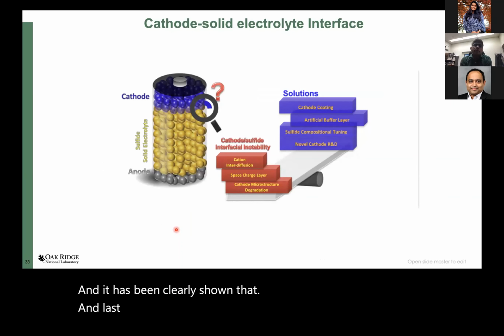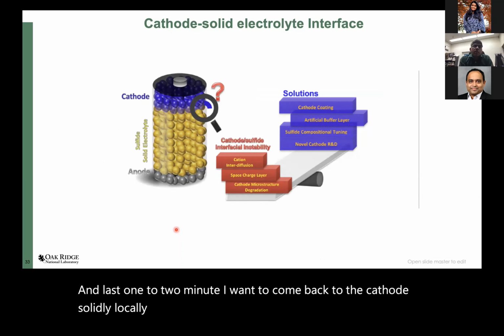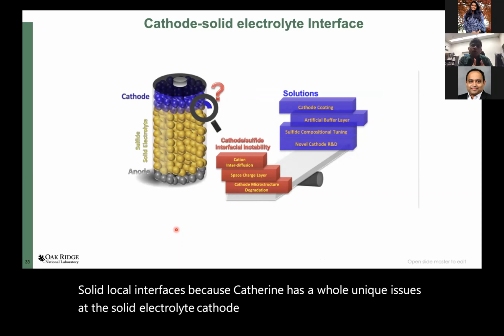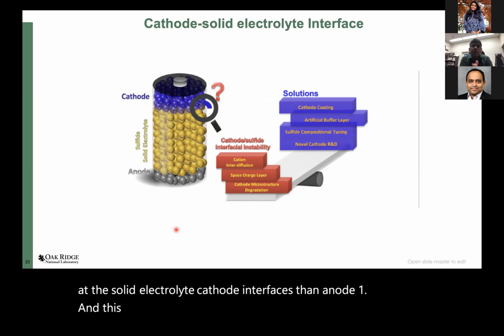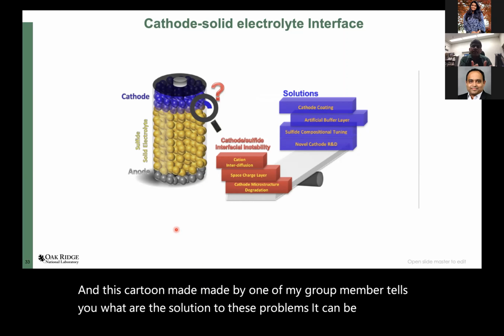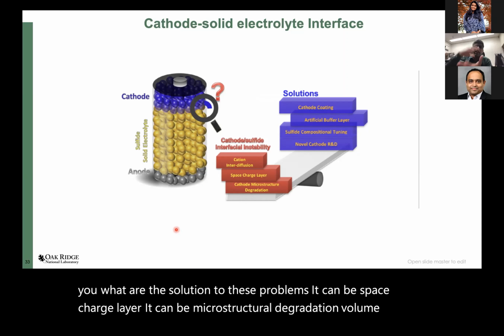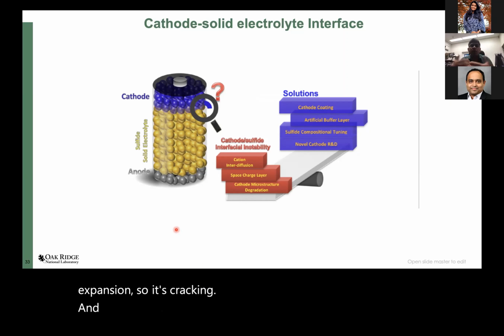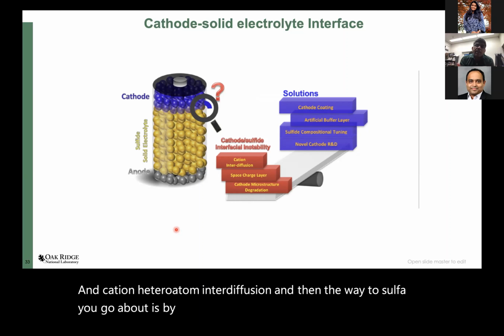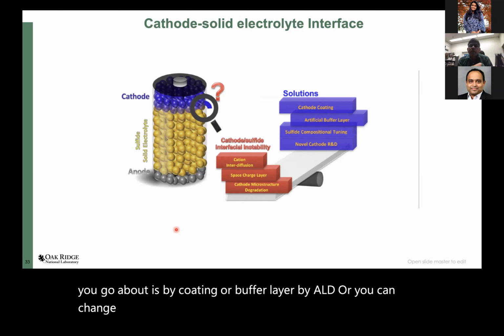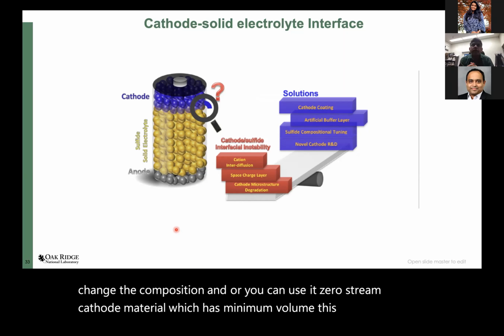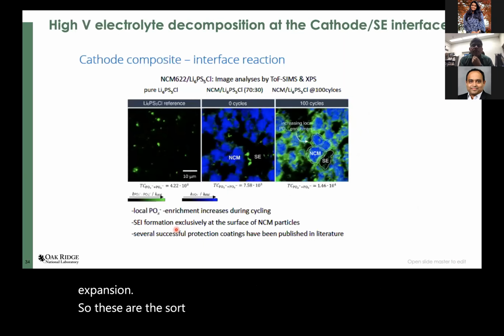In the last one or two minutes, I want to come back to the cathode solid electrolyte interfaces, because the cathode has a whole set of unique issues at the solid electrolyte cathode interface compared to the anode one. This cartoon made by one of my group members tells you what the problems are. It can be space charge layer, microstructural degradation, volume expansion, so cracking, and cation heteroatom interdiffusion. The way to solve them is by coating or a buffer layer by ALD, or you can change the composition, or you can use a zero-strain cathode material which has minimum volume expansion. So these are the fundamental processes that we need to consider.